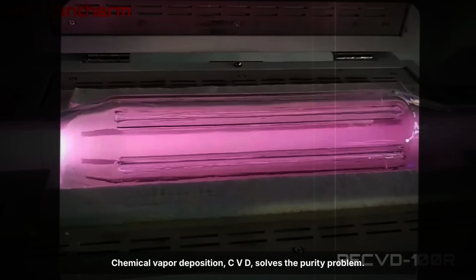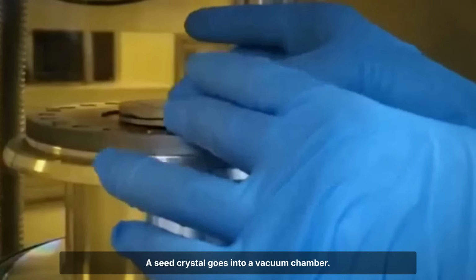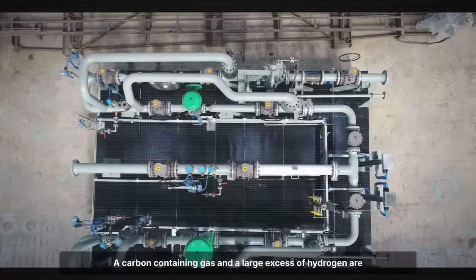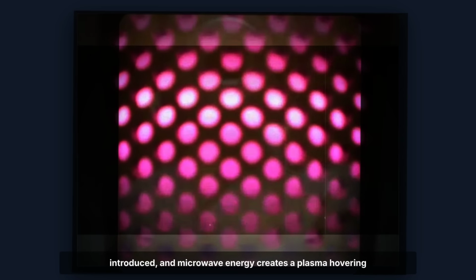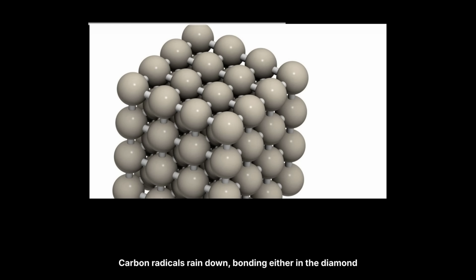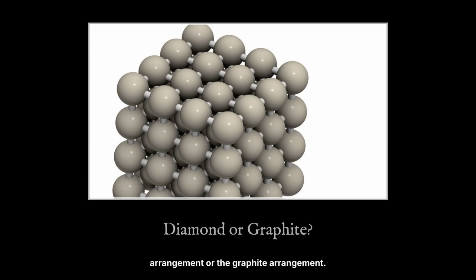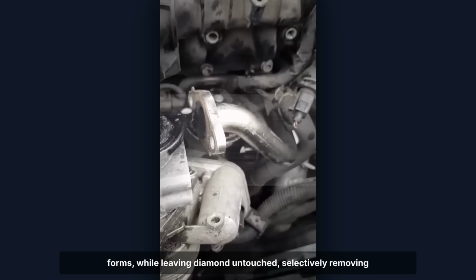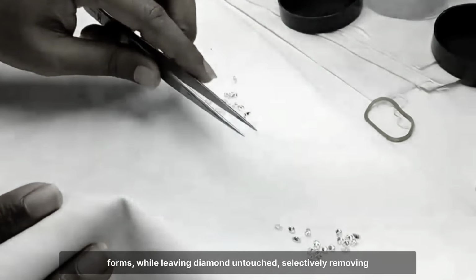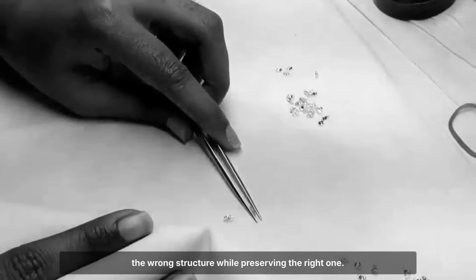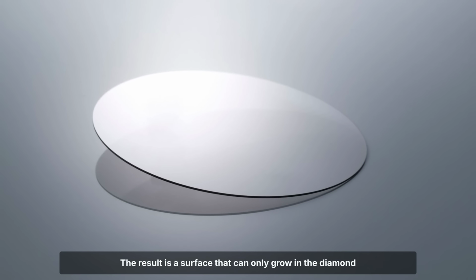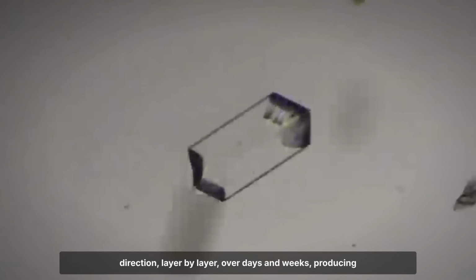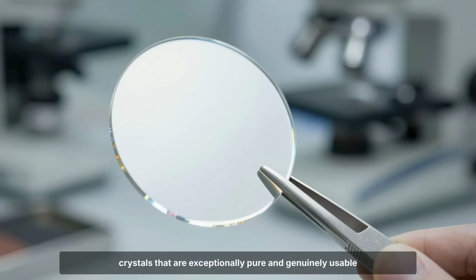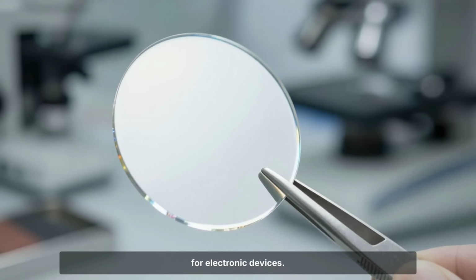Chemical vapor deposition, CVD, solves the purity problem. A seed crystal goes into a vacuum chamber. A carbon containing gas and a large excess of hydrogen are introduced, and microwave energy creates a plasma hovering just above the seed surface. Carbon radicals rain down, bonding either in the diamond arrangement or the graphite arrangement. Atomic hydrogen continuously etches away any graphite that forms while leaving diamond untouched, selectively removing the wrong structure while preserving the right one. The result is a surface that can only grow in the diamond direction, layer by layer, over days and weeks, producing crystals that are exceptionally pure and genuinely usable for electronic devices.